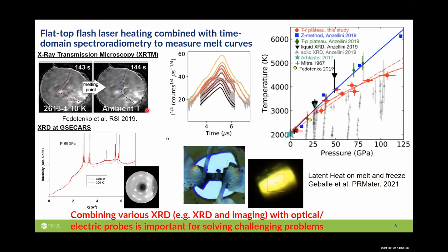So I promote the technique which has been developed by Zach Geballe, and that actually doesn't include any laser heating. So he essentially makes a kind of breach in the diamond anvil cell, and it passes a very short electric current.